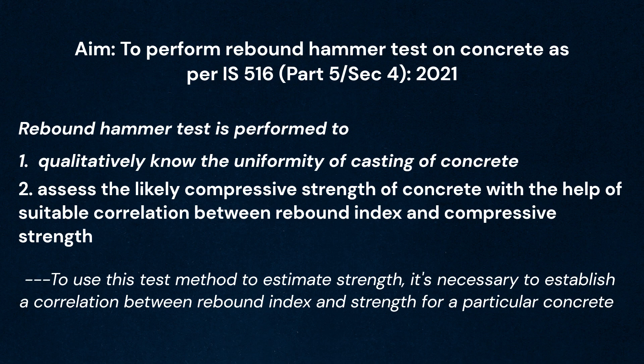To determine the likely compressive strength of concrete, a correlation between rebound index and compressive strength should be established. This can be done by measuring both the rebound index and compressive strength simultaneously on project-specific concrete cubes.